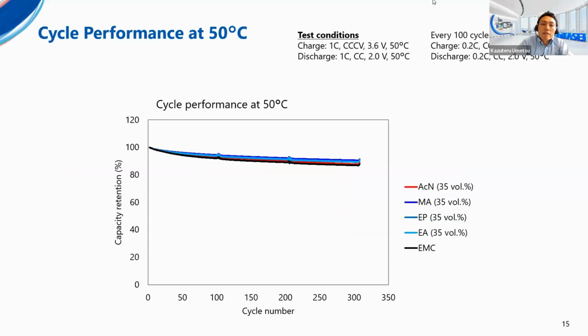Cycle performance was evaluated at 50 degrees C. The conditions were 1 C charge and 1 C discharge from 3.6 to 2 volt, and 0.2 C every 100 cycles. As you can see, all electrolytes showed stable performance for 300 cycles. So in this way, it was found that esters and acetonitrile have the potential to significantly improve output characteristics due to their high ionic conductivity without compromising the durability of existing carbonate electrolytes.